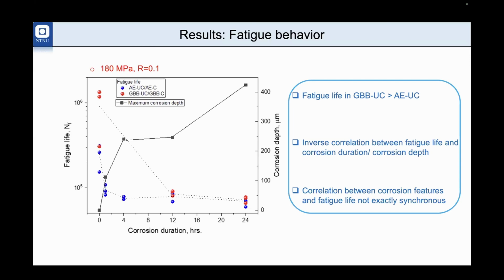Surprisingly, the corrosion depth increases almost consistently with increase in corrosion duration. So even though there is an inverse correlation between fatigue life and corrosion duration or corrosion depth, this inverse correlation is not exactly synchronous. And why is that? That's because fatigue is a very local damage. It requires just maybe 2 or 3 corrosion pits or a tiny intergranular crack itself to initiate the crack. So even if there is a further increase in corrosion damage in terms of maximum corrosion depth, that is not very influential in further accelerating the fatigue damage. In other words, the fatigue damage gets saturated.